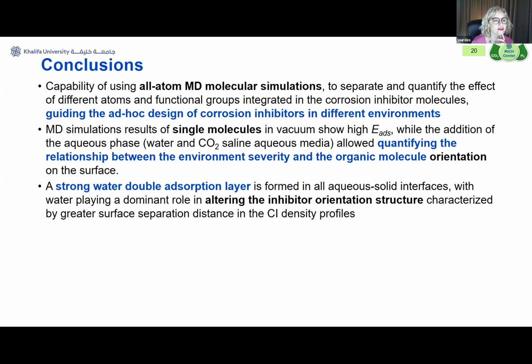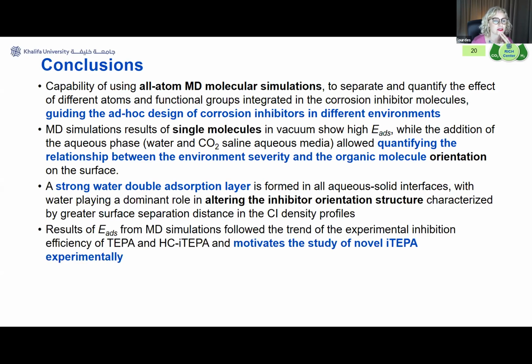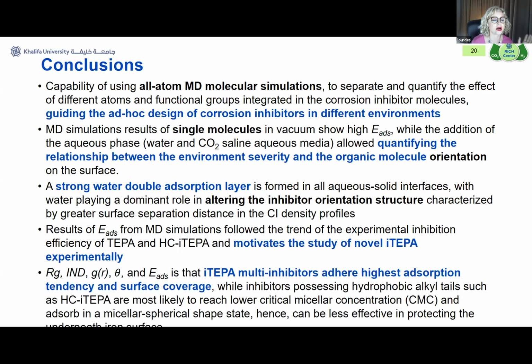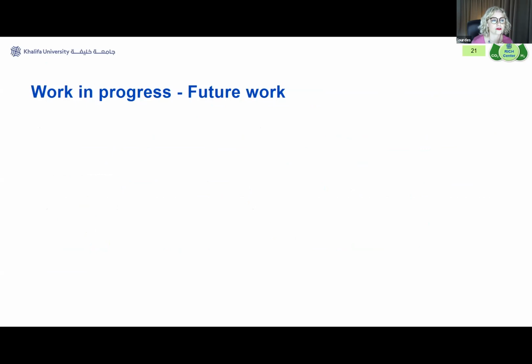We have also observed that this strong water double adsorption layer influences the whole adsorption behavior, and the role of water is key in altering the inhibitor orientation on the surface and then the performance of these molecules. Results from all the simulations we have obtained really guide into using the iTEPA molecule as a better corrosion inhibitor than the other two molecules.